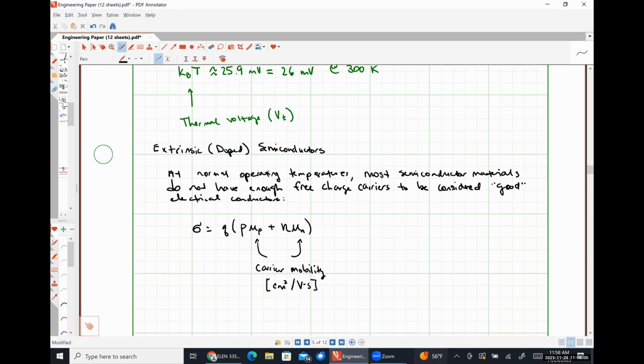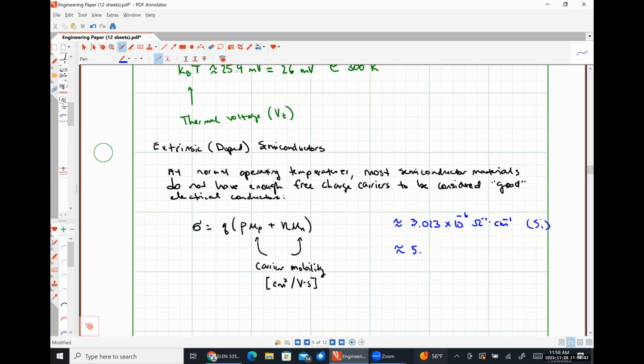So for silicon at room temperature, with intrinsic silicon, meaning no dopants whatsoever, this is about 3.013 times 10 to the negative 6 per ohm per centimeter. As a point of reference, let me write this down, this is approximately 5.952 times 10 to the positive 5 per ohm per centimeter for copper at 300K.